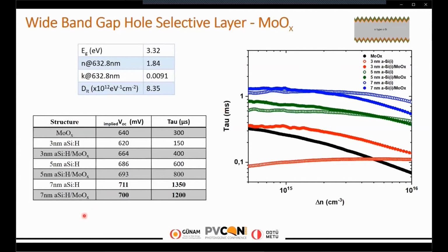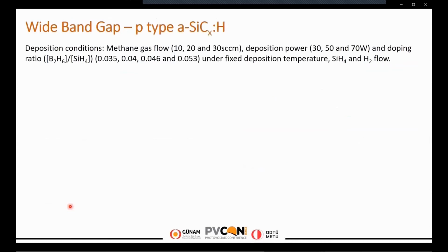At this point, we found the optimum thickness of amorphous silicon as 7 nanometer, and we insert this stack layer on the solar cell structure. Let's continue with the second wide bandgap material, which is P-type amorphous silicon carbide. For the optimization of P-type amorphous silicon carbide, we have changed methane gas flow, deposition power, and doping ratio under fixed deposition temperature, silane, and hydrogen flow.